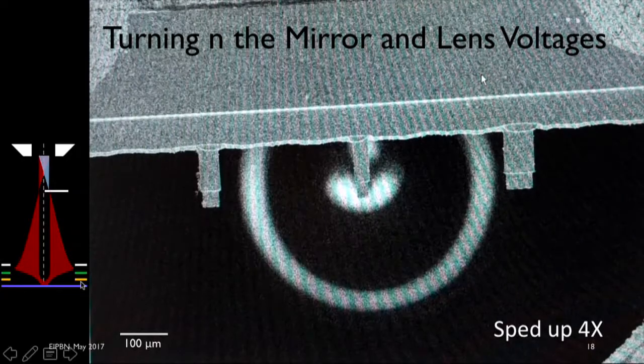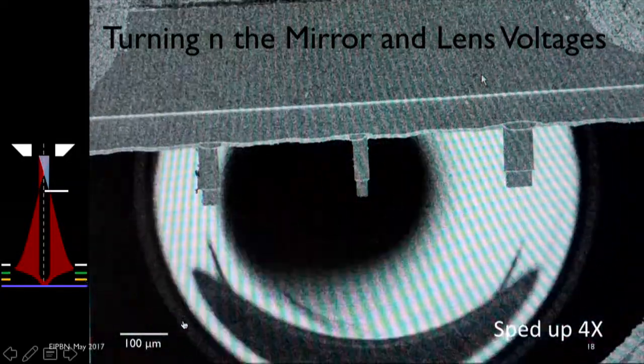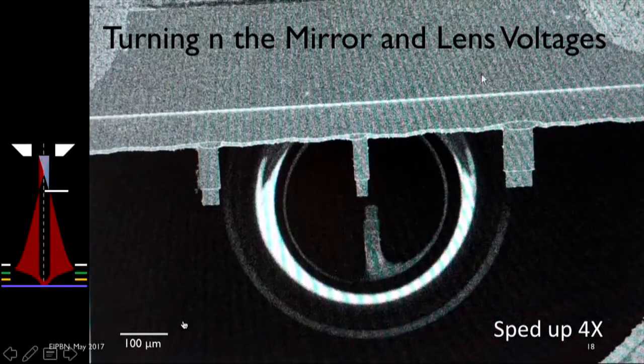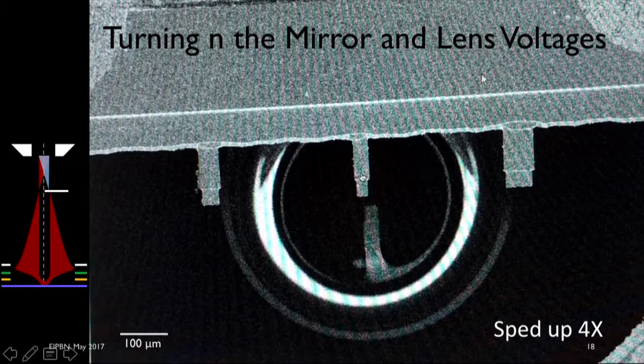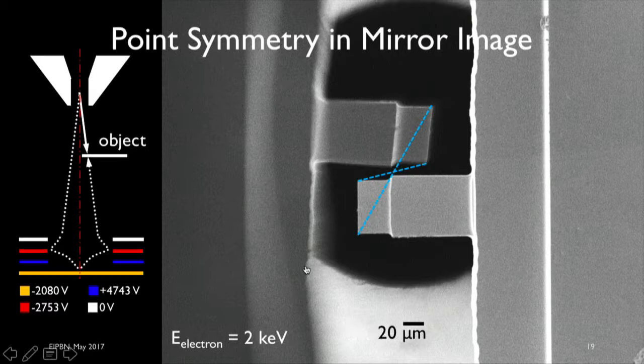And as I tune the yellow and the green electrodes, you see that an image of the bottom surface of the cantilever is forming. That's because I'm focusing the reflected beam on the bottom surface of this cantilever. So this is the top surface of the cantilever, and this is the bottom surface of the cantilever that we can see by scanning a focused reflected beam on the bottom surface. When I further tune these electrodes, I can produce a much sharper image of the bottom surface. Everything you see on the right side of this image is a direct SEM image of the top surface, whereas everything you see on the left side is the beam going through a reflection and refocusing on the bottom surface of the sample. If I turn off these electrodes, the image on the left would actually disappear. We would only see the image on the right.